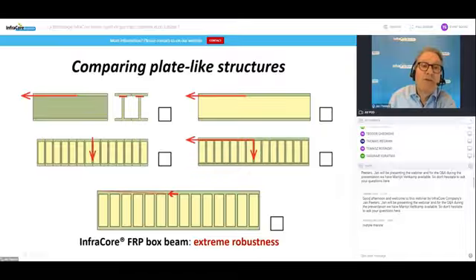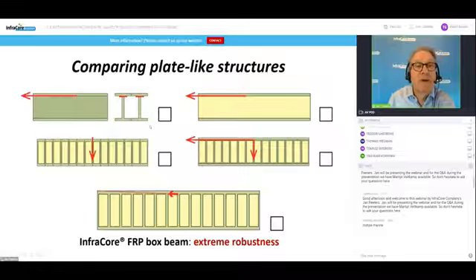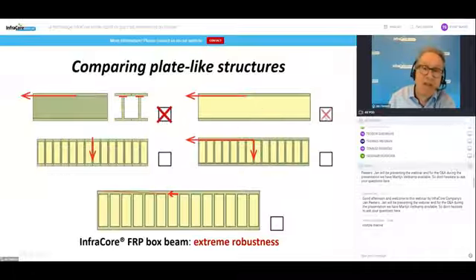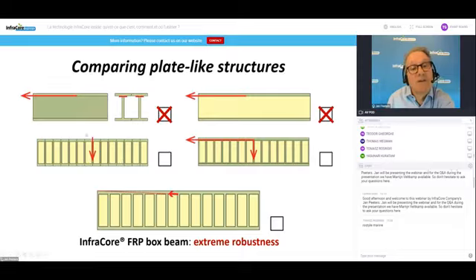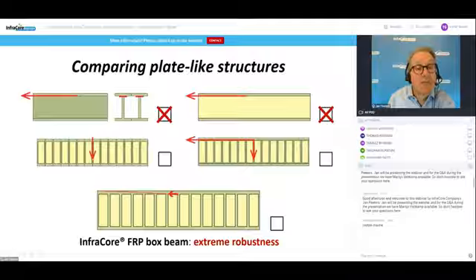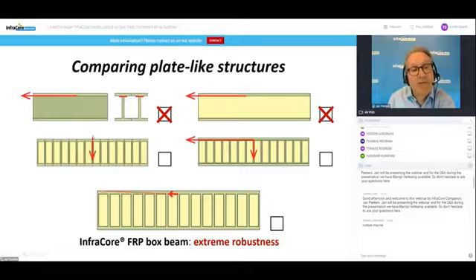There are alternatives, of course, to make a beam plate-like structure. You can take some pultrusion panels or beams next to each other, but when you hit them, you get a very high risk of debonding between the flanges and the web. So that is not a robust solution. We talked about the sandwich structure is not a robust solution. Alternative could be a multi-box beam. So these are beams fully wrapped and then bonded together. When you hit that, your fracture surface, which is unimpeded by fibers, will be in vertical direction, so your bridge can split. That is not a solution.